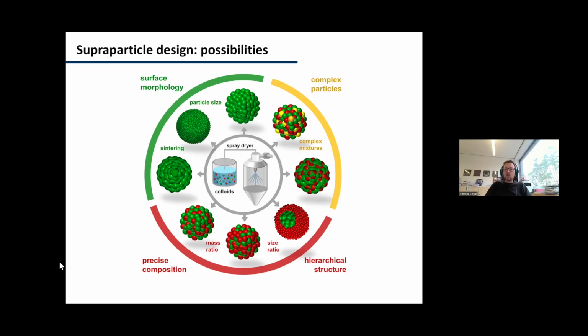And in our case, we can really accommodate both additives by mixing them in, or even multiple additives into the material without compromising the overall shape and structure of the powder itself. And that, in my view, is a fairly big advantage. Plus, of course, the powder itself just flows very well, which facilitates the printing process.